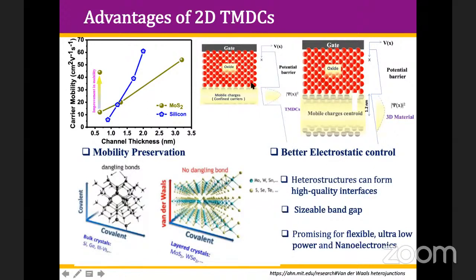You can see here, for example, the FET configuration, the gate oxide and 2D material. So there is a quantum well, and you can confine the charge carriers very well because layer by layer deposition is there, and you can make a monolayer or bilayer. Whereas in the case of conventional 3D material, with the gate oxide and 3D material, the quantum well is not well defined because the thickness is not well defined and your wave function is like this. So the one advantage of 2D material is that you can preserve the mobility.